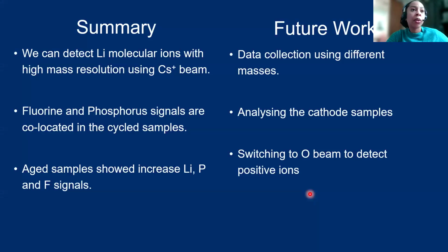So in summary, we can detect lithium molecular ions with very high mass resolution using the cesium beam. We have fluorine and phosphorus signals that are co-located on the cycled samples, and they also seem to not be depositing very strongly on the flat basal planes of the material. And each sample shows increased lithium, phosphorus, and fluorine signals. So future work would be to continue developing that database or library of high mass resolution spectra so we can continue to study these materials.